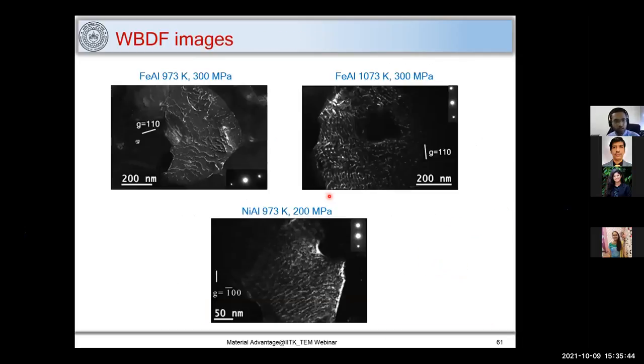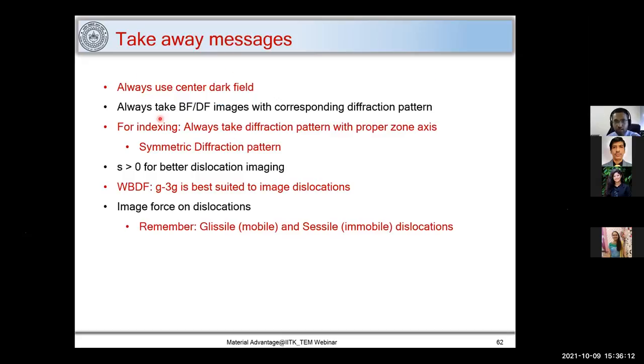So there are certain weak beam dark field images which I have taken. You can see the array of dislocations gliding on some planes, the 110 plane, and you can see the climb of these dislocations. You can identify glide and climb just based on your weak beam dark field images, and you can understand how the partials or superpartials can form in the case of intermetallics, also using weak beam dark field conditions.